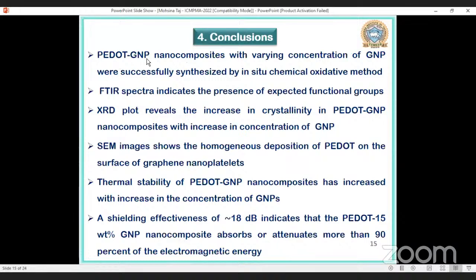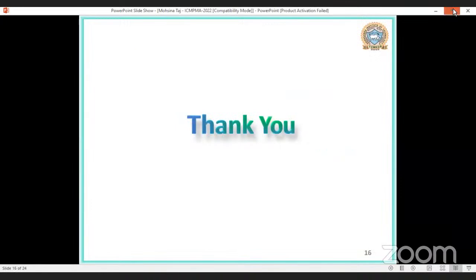We have successfully prepared PEDOT graphene nanocomposite using in situ chemical oxidative polymerization method. Using FTIR and XRD studies, we confirmed the formation of PEDOT graphene nanocomposite. SEM images indicated the homogeneous deposition of PEDOT on the surface of graphene nanoplatelets. And the thermal stability of the PEDOT graphene nanocomposites has increased with increase in the concentration of graphene nanoplatelets. And we have obtained a nearly 18 dB of shielding effectiveness. This indicates that material can attenuate 90% of the incident electromagnetic radiation. Thank you.